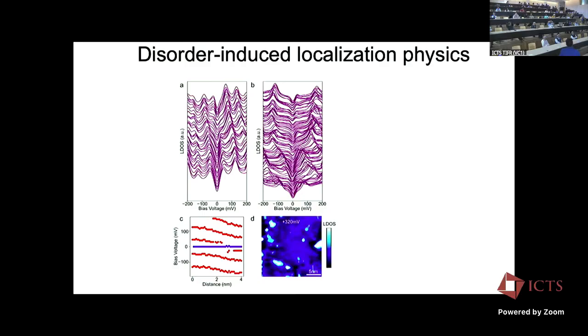Yeah, gating is tough because these are very good metals. Okay, but the screening we can change. In fact, for this experiment, we put it on a gold substrate to really screen out interactions as much as possible. But we can change that. We don't have to put it on this gold. Right. Yeah, so that I think is an interesting suggestion. It is still open. Okay.